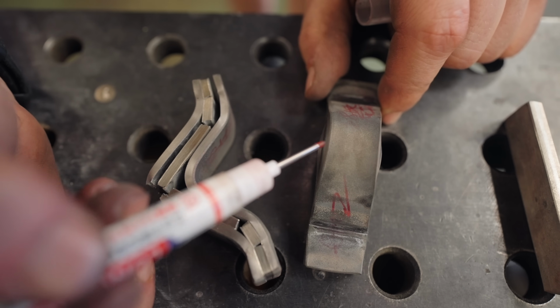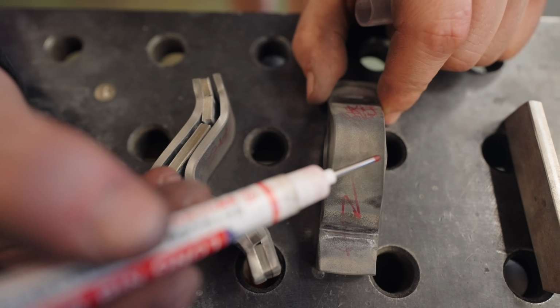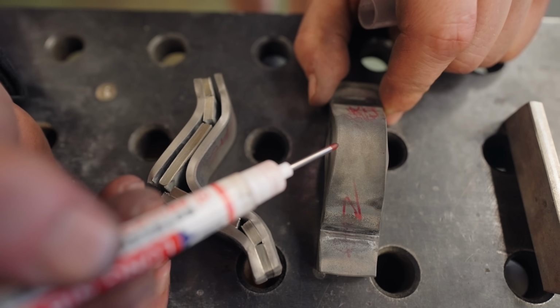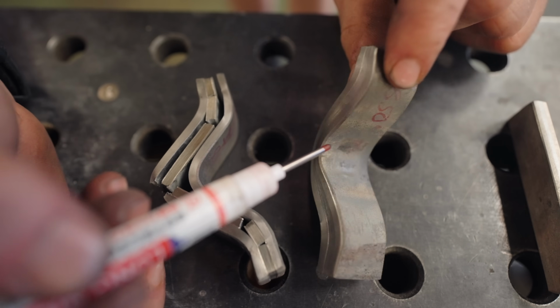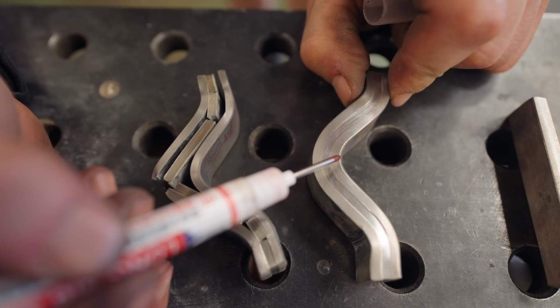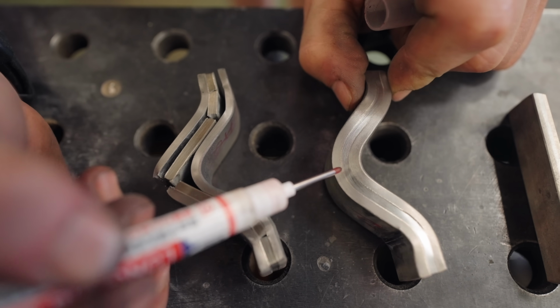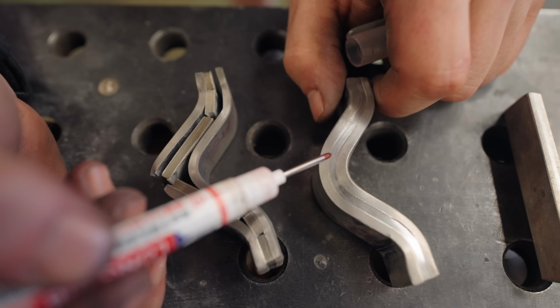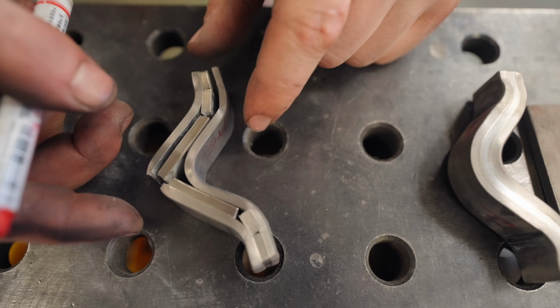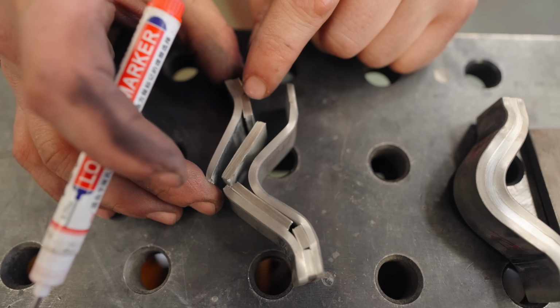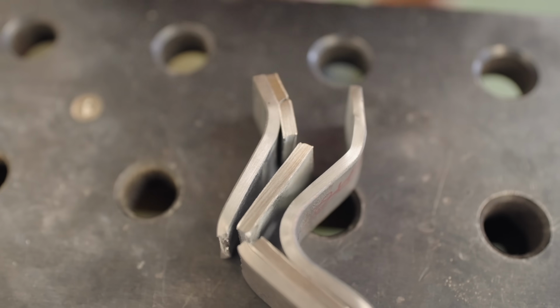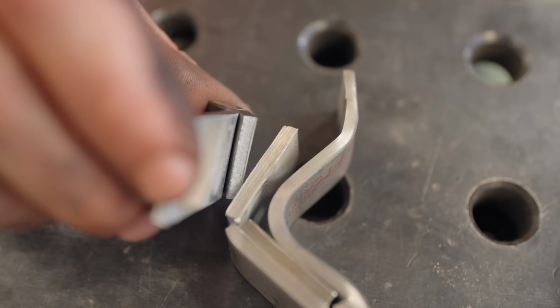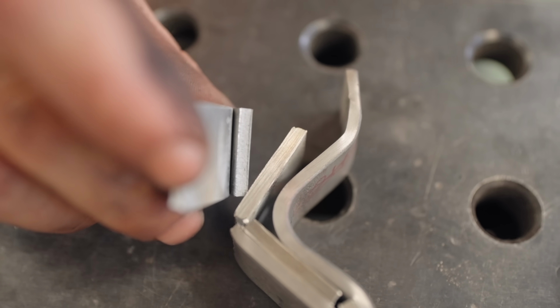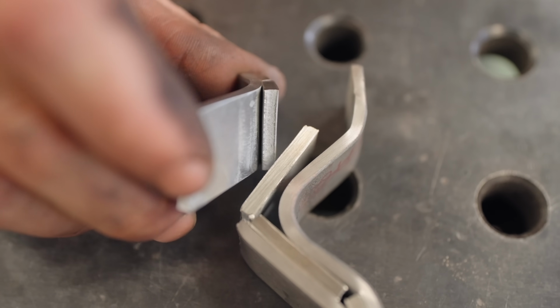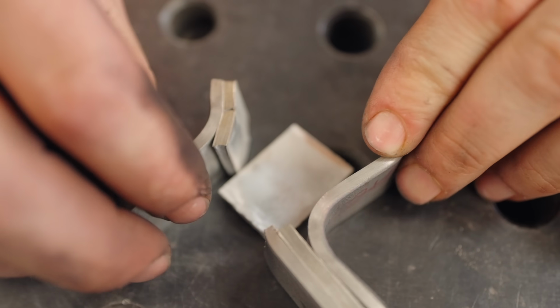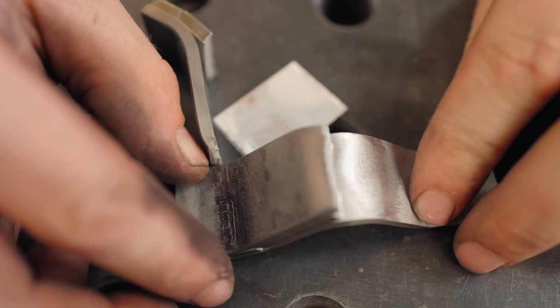Look at that plastic deformation through there as it's taken the bend and it has stretched the titanium on the tension side. It has upset the titanium on the compressive side, and the joint through there withstood it. That's a remarkably good titanium to steel bond. However, of course, on the hardened piece, it is not surprising that the steel broke. The steel is now in a much more brittle state, so I expect the steel to break when we're trying to force it around a bend that's that tight at 58 Rockwell. And obviously it appears like we also delaminated the steel from the titanium.